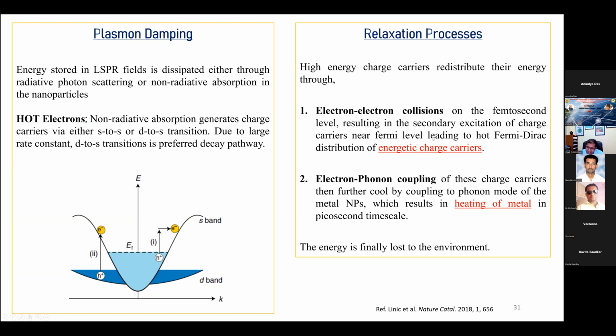If you cannot even use these hot electrons, then they undergo electron-phonon coupling. A phonon is a vibrating atom, so the electron collides with these vibrating atoms, and all the energy absorbed from the sun is converted into thermal energy localized on the surface of the gold nanoparticle. So if my reaction is happening on the surface, that reaction gets this energy and the reaction rate can increase. So you can have a hot-electron-assisted reaction or a photothermal-assisted reaction.